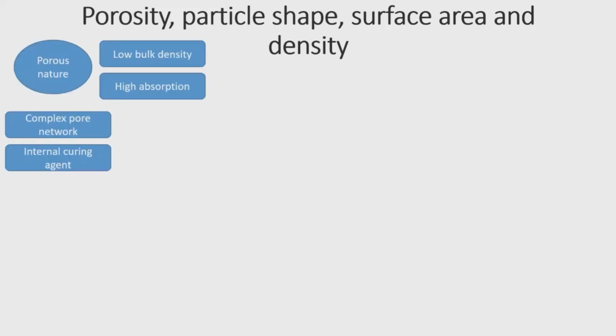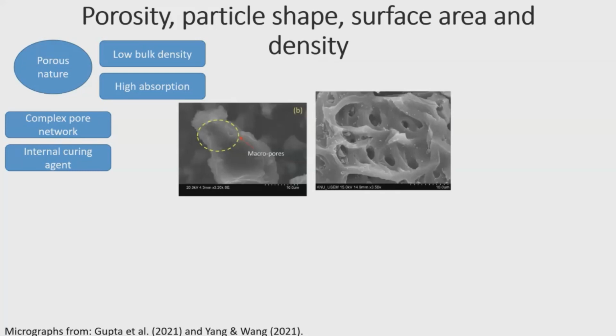Under porosity, particle shape, surface area, and density, we identify biochar as a pyrogenic residue of biomass thermochemical conversion. This is a process where oxygen conditions are limited, during which water evaporation occurs first, then is followed by the release of volatiles, and finally the setting of porous carbonaceous ashes. In the broadest sense, biochar is a charcoal-like solid material, typically composed of carbon, of porous carbonaceous nature, and low bulk density. This allows biochar, from a structural point of view, to have high absorption, hydrophilicity, a complex pore network, and to function as an internal curing agent in cementitious composites. In this micrograph, we can appreciate the porous nature of biochar.